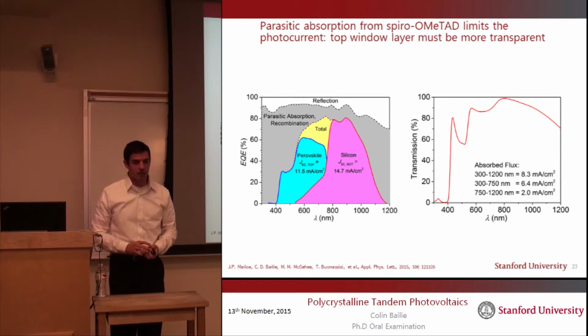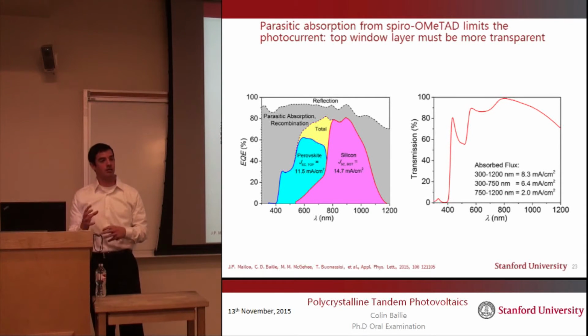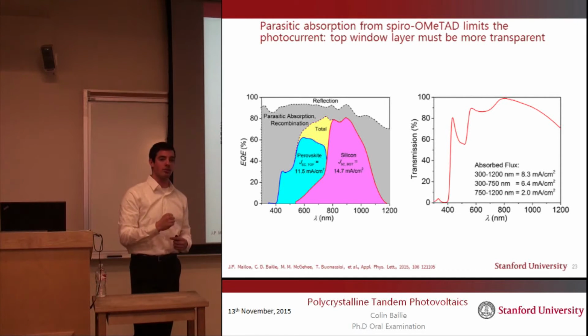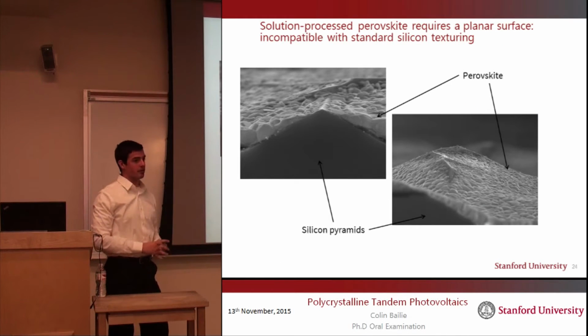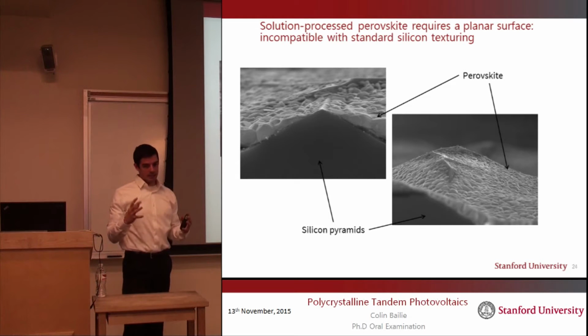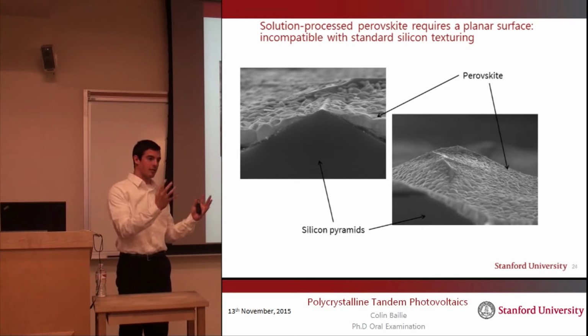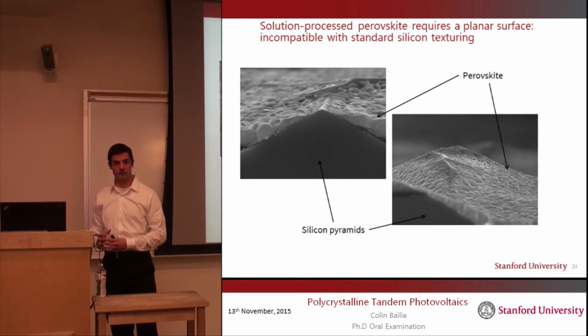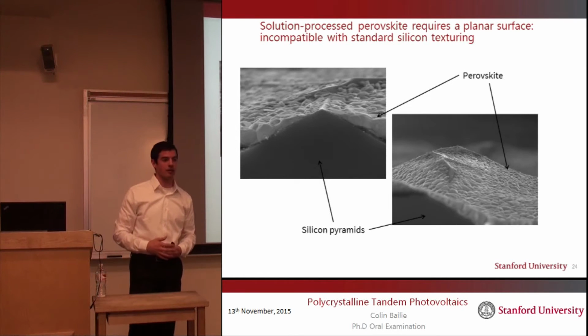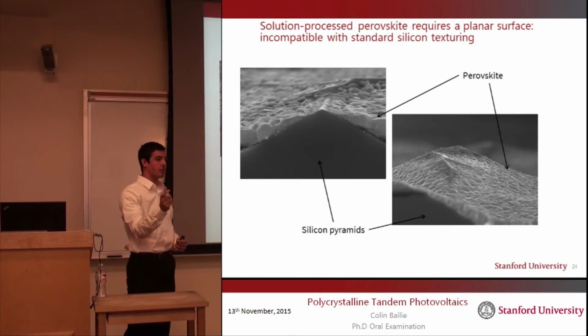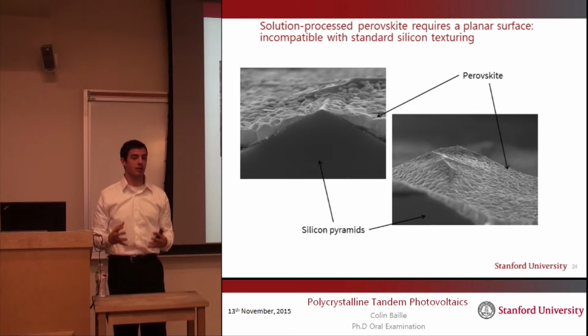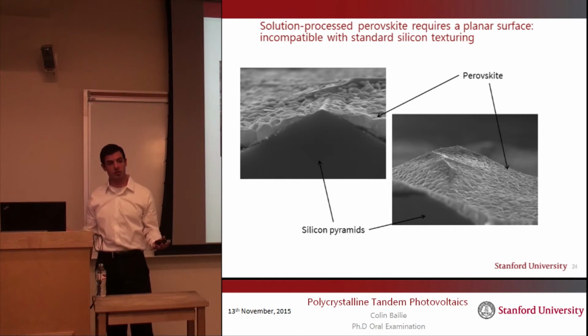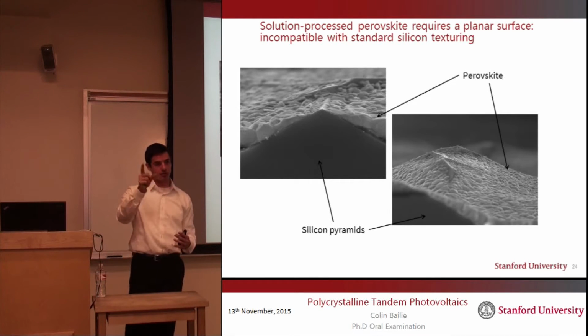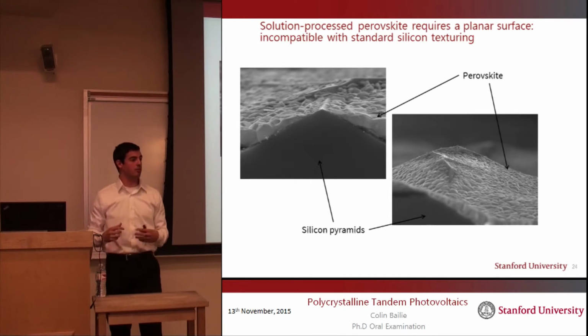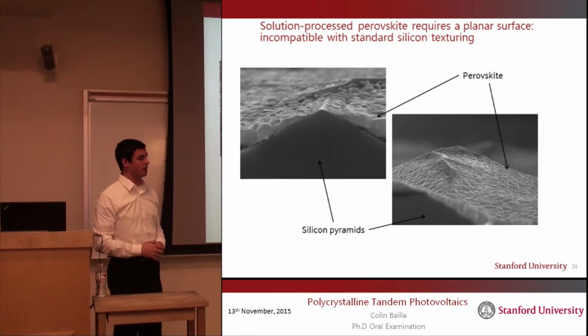So let's pretend that this is solvable and we have our 18% tandem. How do we then go from this 18% tandem to that magical 30% red dot in the sky? And the answer is that maybe it's a little bit difficult to go about doing that, because there is a difference in how you would like to make a silicon solar cell and how you might like to make a perovskite solar cell. A silicon solar cell, throughout half a century of design optimization, has ended up with a textured top surface and a textured bottom surface, making silicon pyramids. And these silicon pyramids are there because silicon, as an indirect band gap absorber, does not strongly absorb the infrared light, and these pyramids serve to have internal reflections, so the infrared light can bounce up and down throughout your silicon solar cell until it has a high probability of being absorbed.